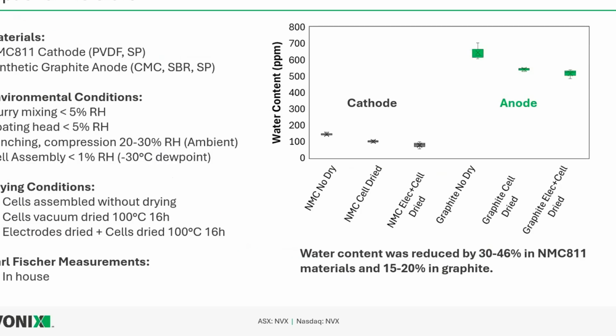So I'm going to go through some details here. This is going to be an in-depth case study. So we use NMC 811 cathode, so higher nickel, maybe a little more sensitive to moisture. Synthetic graphite anode. In our environmental conditions, our slurry mixing is less than 5% relative humidity. Our coating head is less than 5% relative humidity.